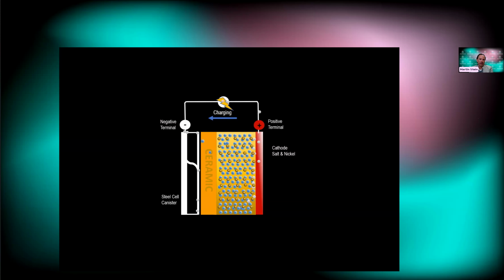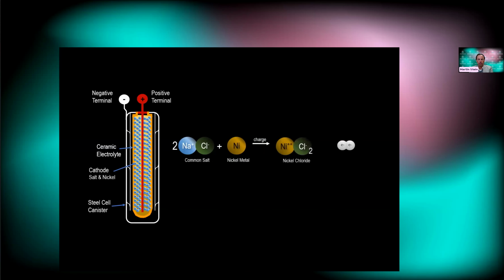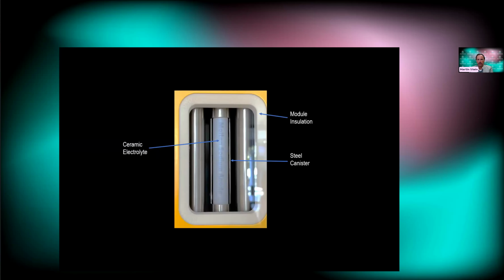Now, when we charge the battery, this is where the chemistry and the reactions happen. The chloride from the sodium chloride sticks to the nickel, and the sodium migrates through the ceramic electrolyte and forms a molten anode between the ceramic electrolyte and the negative stainless steel canister. And that's a cross-section of how it looks.